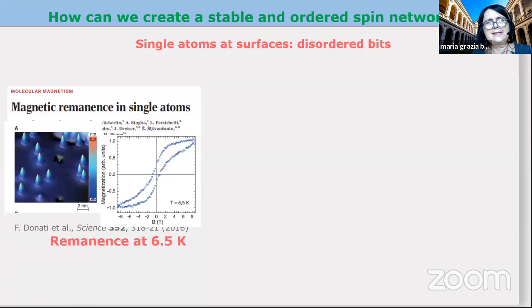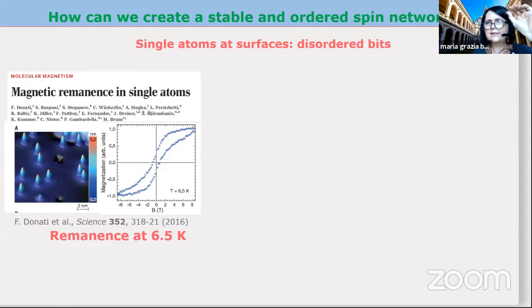So let me show you a very interesting paper published 4 years ago, I think, when they studied the magnetic remanence of a single atom deposited on a surface. This is holmium deposited on a surface of magnesium oxide. And then you will see you will have disordered atoms on the surface. And then they measured the hysteresis. And there is a remanence, but the remanence is only at 6.5 Kelvin. So at very low temperature.